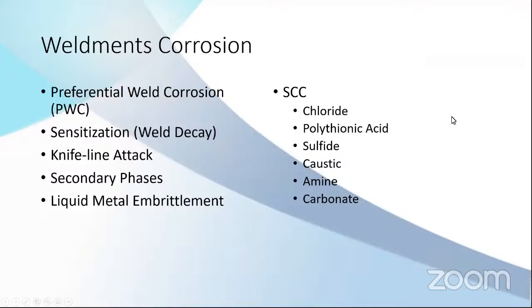And what are the common corrosion types that happen in the weldment area? I have compiled some of the corrosion that I know. This may not be everything, but this is what I know mostly, and this is what I normally mitigate when I write the specification for corrosion prevention. So there will be preferential weld corrosion, sensitization, knife line attack, secondary phase precipitation, liquid metal embrittlement. These are all what I consider metal loss corrosion, where the metal will be losing material over time.